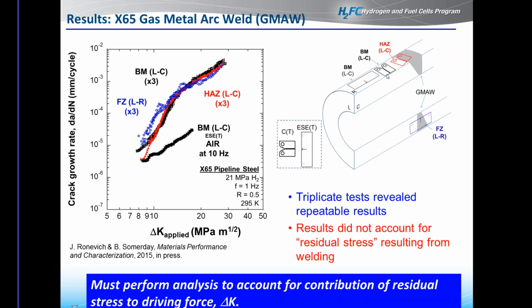And so what we have here are the fatigue crack growth curves. So just backing up slightly, what this curve really represents is, on the x-axis, we have the delta K applied. And really that is the stress intensity factor applied, or in other words, the driving force that we're supplying to get something to happen. The y-axis is the crack growth rate. That's really the material response. So we're basically applying a driving force and we're measuring the material response.